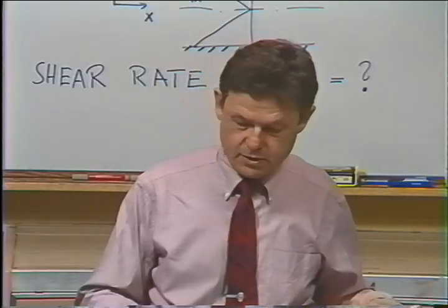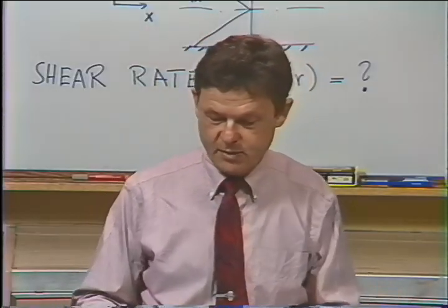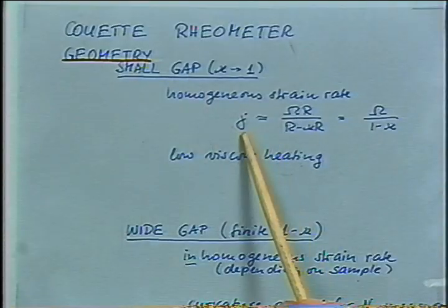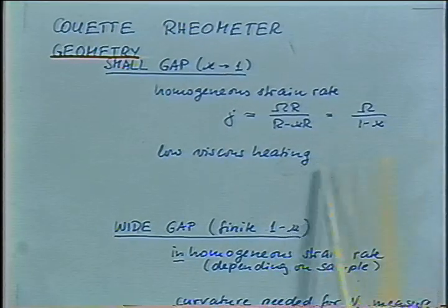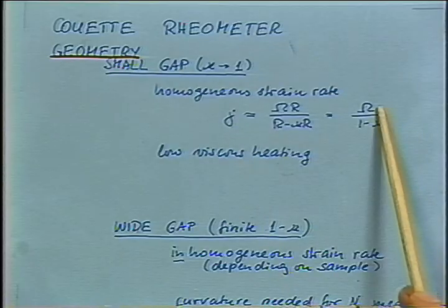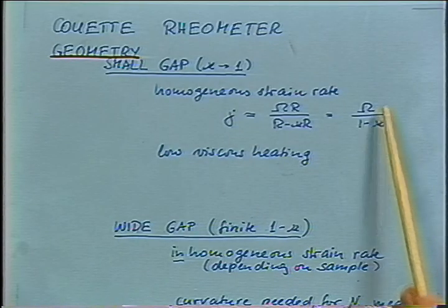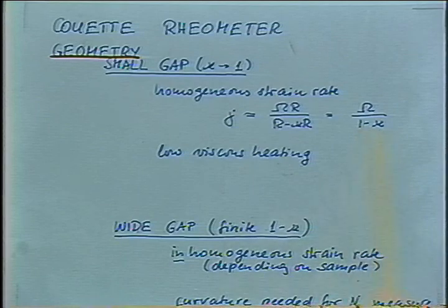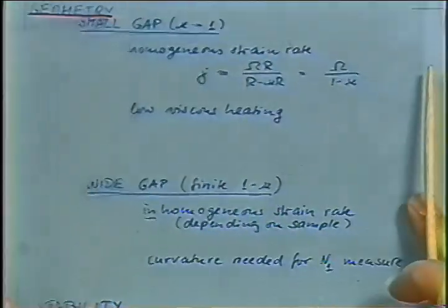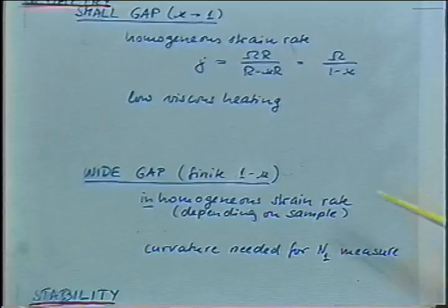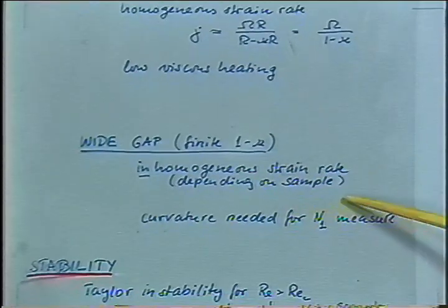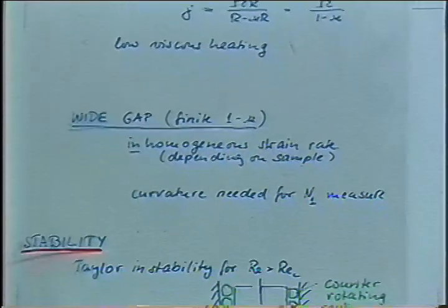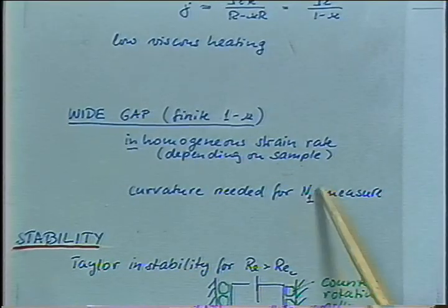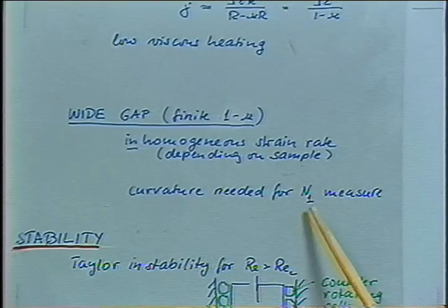However, as you already guess, if the gap is very small, then the velocity profile is linearized, and you immediately get the shear rate from the rotational speed of the outer cylinder divided by the gap width. The shear stress is also linearized, so you can obtain your viscosity directly. In case of a wide gap, the flow is inhomogeneous, and you have to do some curvature correction. But if you want to measure the first normal stress difference, you need curvature.